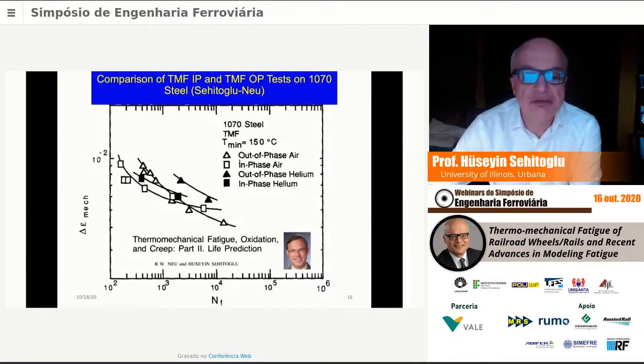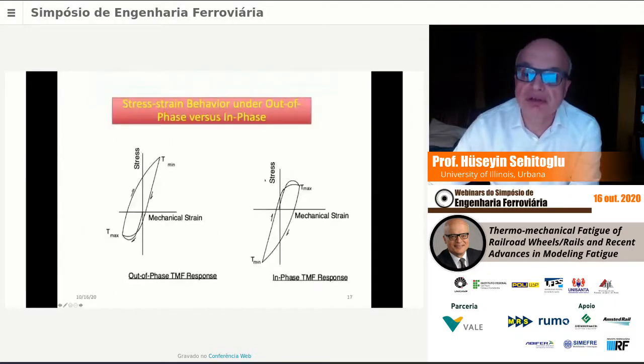So you could see here in our results, we're also getting out-of-phase and in-phase results. You could see that the in-phase lives are shorter at short lives, but there's a crossover here that's a bit more evident, and the out-of-phase results are shown to be lower at longer lives. So in-phase is more detrimental here, out-of-phase more detrimental here. There is an effect of environment. We did conduct some experiments in an inert environment, and the fatigue lives are longer. It's difficult to run these experiments, of course, but clearly there is an effect of oxidation on the results.